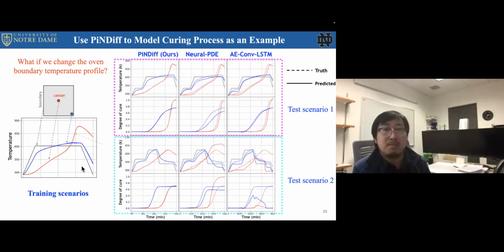Okay, so then we do some other tests. If we change the oven temperature profile, this is the training scenario, and then we arbitrarily create some autoclave temperatures, which go up, remain constant, and then go up again and remain constant. This one is not quite different from the training one. You can barely see the difference between the dashed line and the solid line. The dashed line is the ground truth and the solid line is our model predictions. But you can clearly see the difference for the other 2 black box data-driven models.